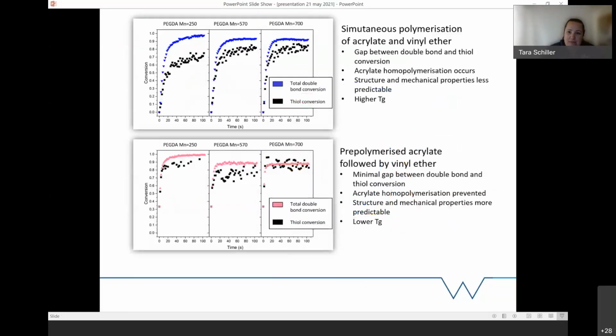What we've done from here is look at the kinetics of the systems and how much conversion occurred. The homopolymerization compared to the acrylate compared to the thiol conversion occurs at different times. So we've got quite a bit of a changeover with the system depending on what we've actually done with it, which is honestly quite nice to see that in some ways the hypothesis worked quite well with this work.